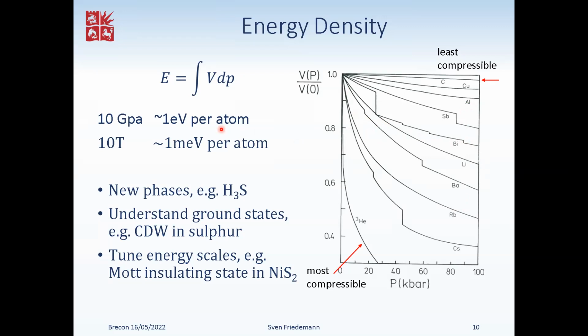Of course, we can't control to shift specific orbits in a specific direction. The material will rather optimize itself to that, but the high energy densities that we have available give hope that a lot of things can happen, and it's in particular about 1,000 times larger than what you can achieve in lab magnetic fields. And we do create new phases, and I'll show the example of hydrogen sulfide later on. We can try to understand ground states, how they interact with each other, and I'll show some results on elemental sulfur. Or we can tune some energy scales like in Mott insulators, and I'll see if I've got time to just flash through what we've done on nickel disulfide.